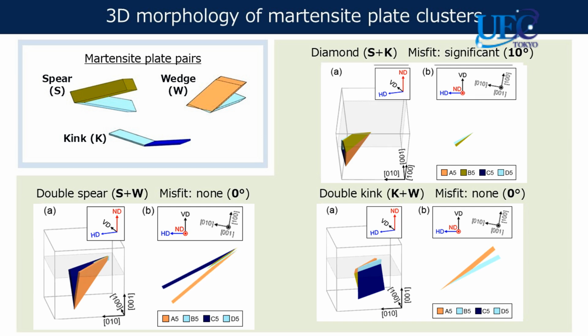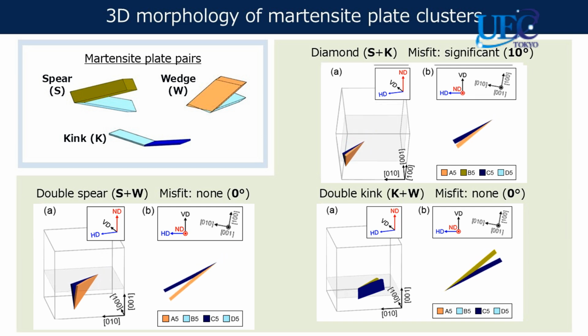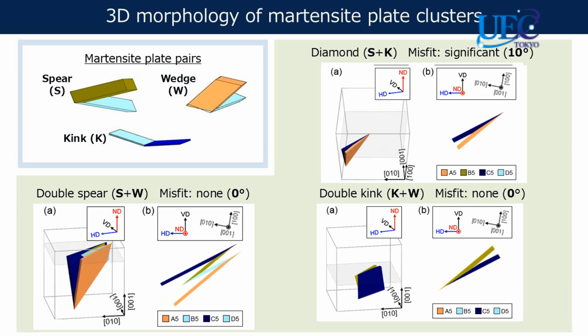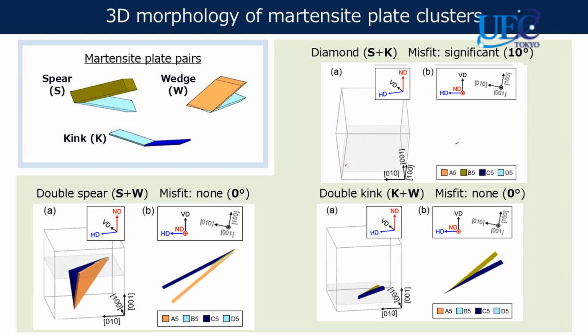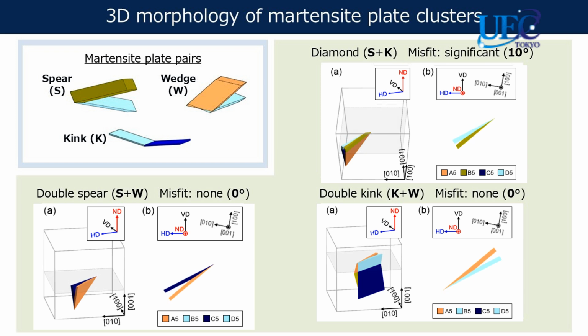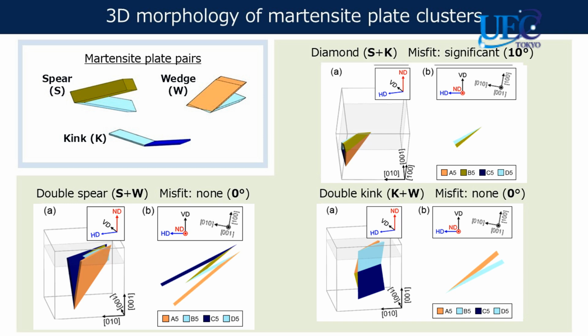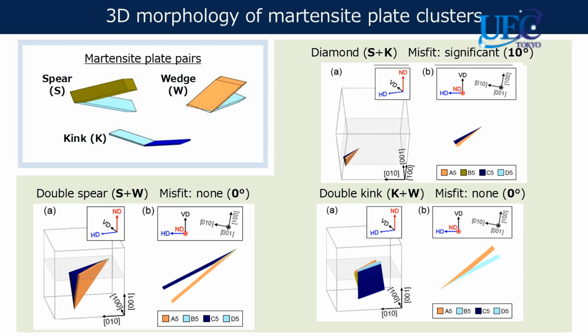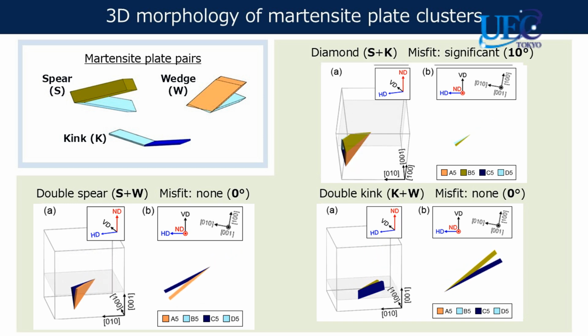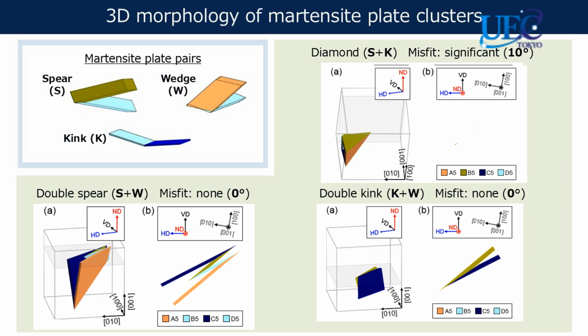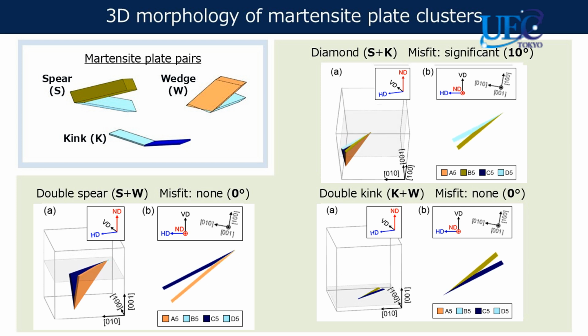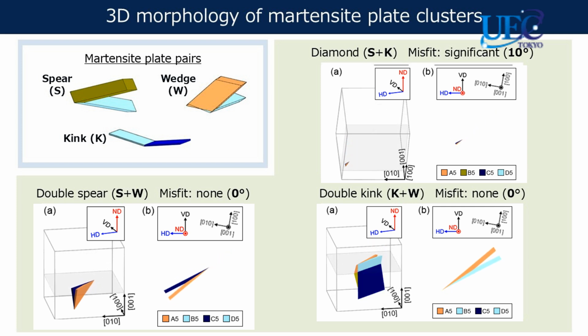Furthermore, 3D morphology can be considered for a martensite plate cluster that combines martensite plate pairs. The three cluster morphologies formed by spear, wedge, and kink pairs are shown here. In microstructure observation, the sample surface is observed, namely, the cross-section of the cluster is observed. So we created a program to simulate the shape of the cluster cross-section.